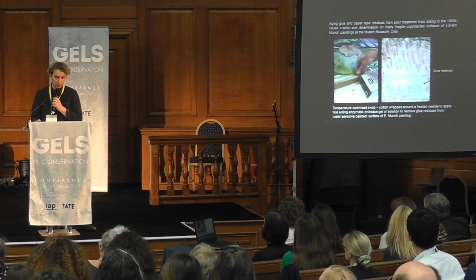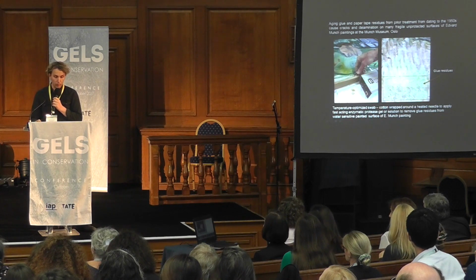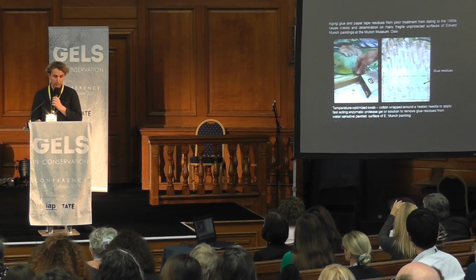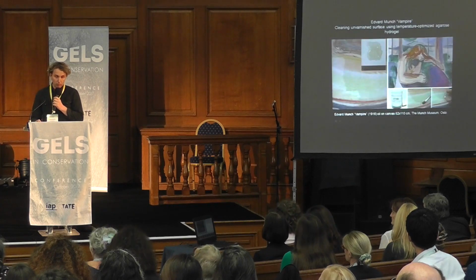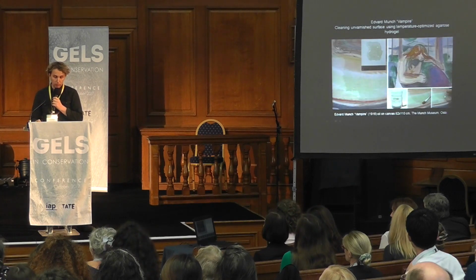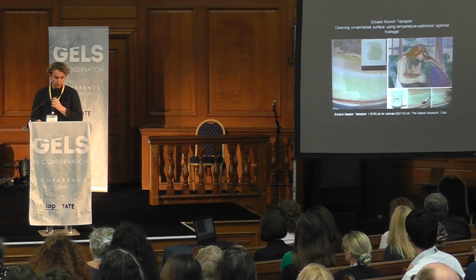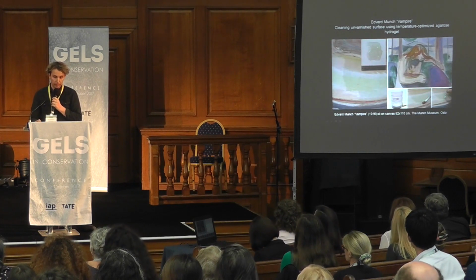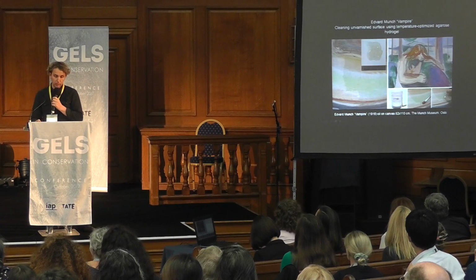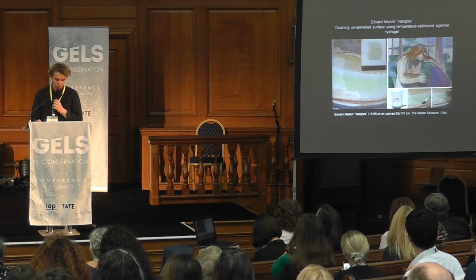We also experimented with a method of applying viscous enzymatic gels using a warmed cotton swab wrapped around a heated needle, quite a handy method for small areas such as edges. Precision heat transfer was yet exploited in another way to clean the unvarnished porous surfaces of Vampire by Edvard Munch. Munch paintings consistently have very fragile surfaces due to his studio practices.